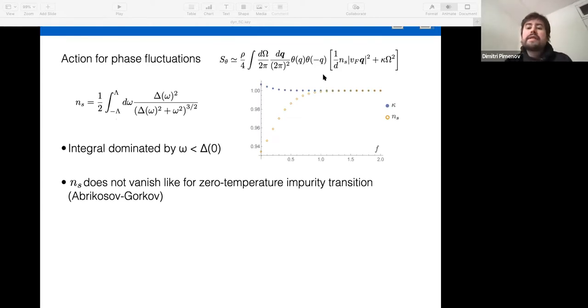And now the superfluid density in this configuration, where the gap function depends on the frequency, can be shown to follow this behavior. And now, if you modify this parameter f, then because the gap function will change, the superfluid density will change. But interestingly, if f becomes larger, so it approaches a critical f, then the superfluid density will be locked to this basically BCS kind of value.